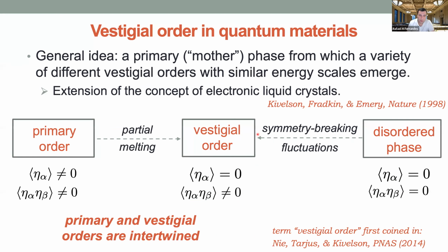So this was an example, and now I can extend this to a much broader context: the idea of a vestigial phase. The idea is I have a primary order parameter, which has to be a multi-component order parameter, which I call eta alpha, where alpha is just the components. When the primary order sets in, this primary order parameter is non-zero; in the disordered phase, the order parameter is 0. But I can build tensor order parameters, or composite order parameters, that are non-zero in the primary phase, non-zero in the vestigial phase, but 0 in the disordered phase. This only happens if this combination breaks a symmetry, which is what I explained before.